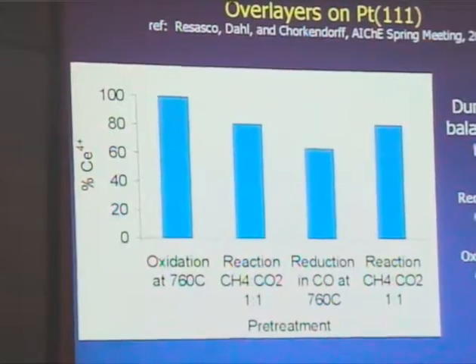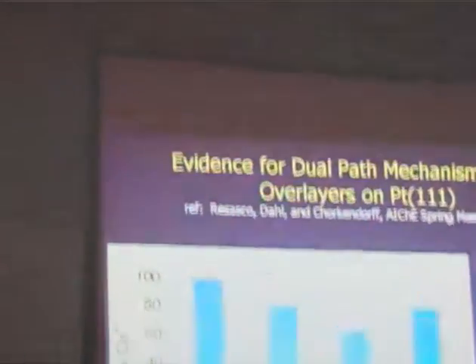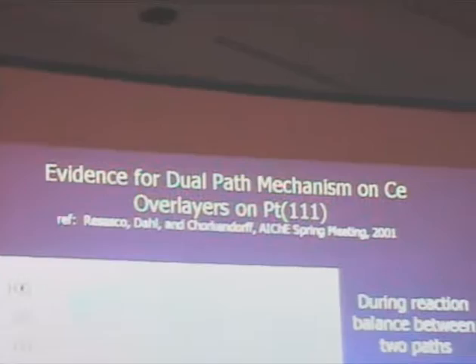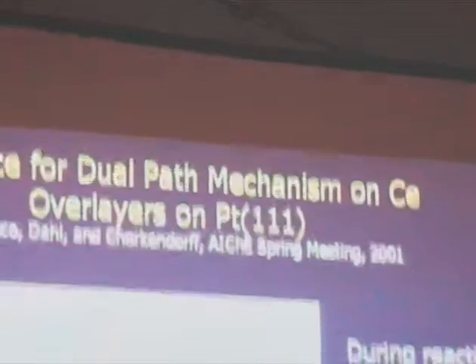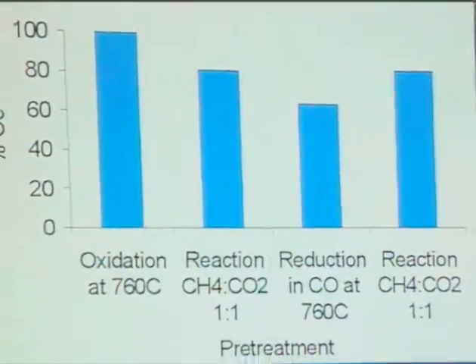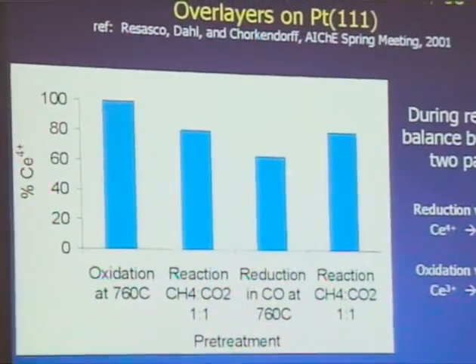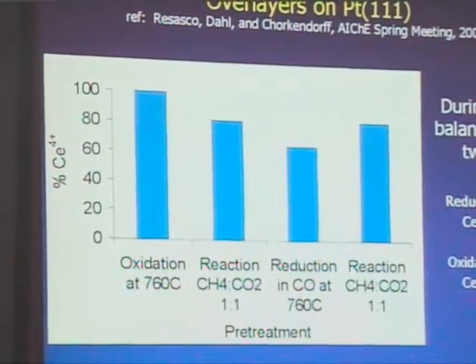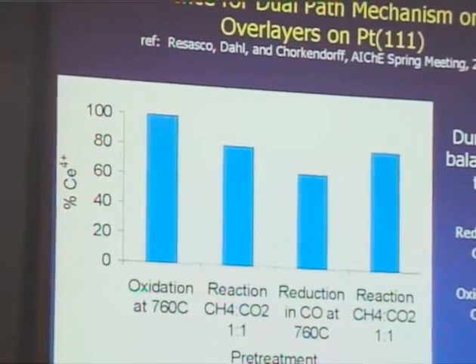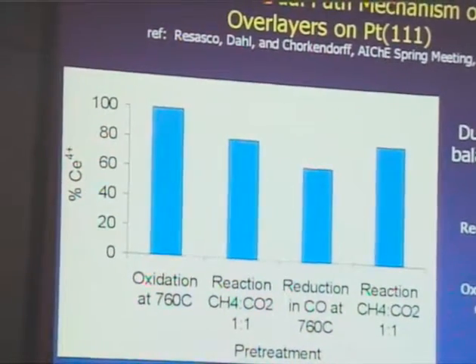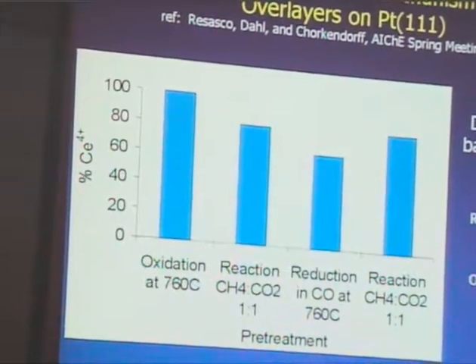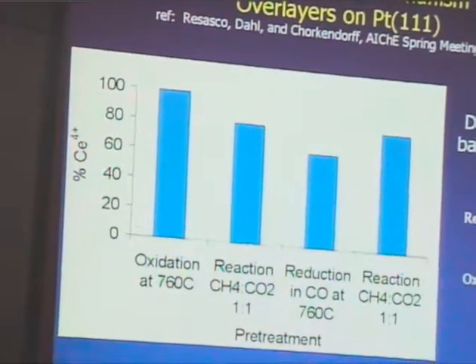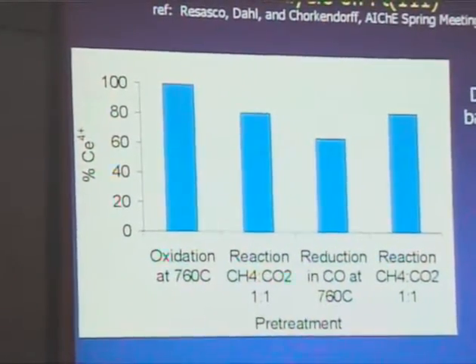A really nice study that was recently done by Resasco and co-workers while I was on sabbatical was to look at the evidence for the dual path mechanism on ceria. What has been done in this study is they've taken ceria overlayers on platinum 111 and done different pre-treatments and different reaction conditions, and then used XPS to measure the fraction or the amount of reduced and oxidized ceria, Ce4+ and Ce3+, on the surface. In this case here, the pre-treatment in the first condition is just oxidation at 760 degrees C, and you see that 100% of the ceria is in the 4 plus state.